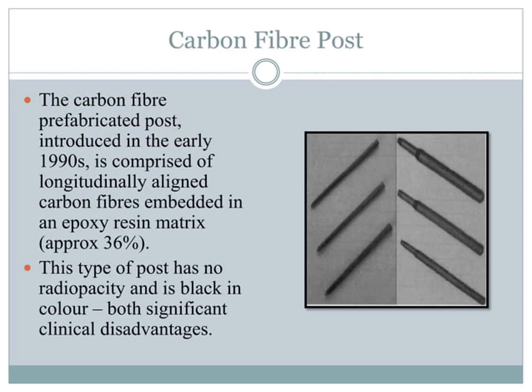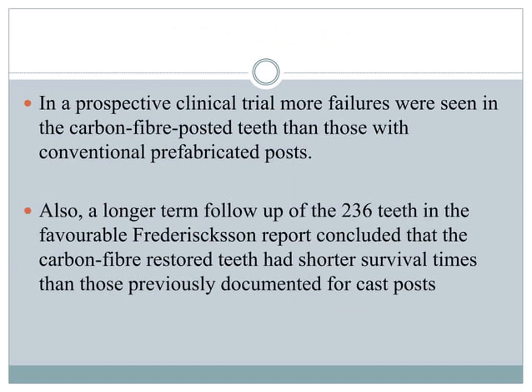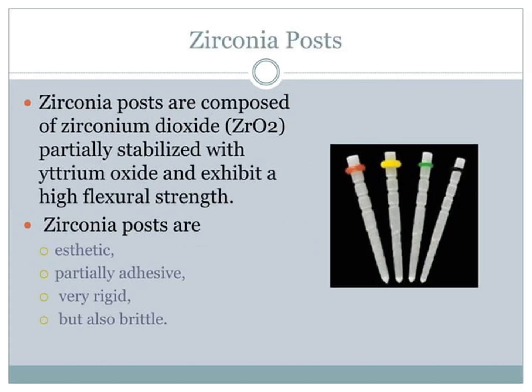Carbon fiber posts were introduced in the early 1990s and are comprised of longitudinally aligned carbon fibers embedded in the epoxy resin matrix. This type of post has no radiopacity and is black in color, both significant clinical disadvantages. In the prospective clinical trials, more failure was seen in the carbon fiber reinforced posts than those with conventional prefabricated posts. Also, a long-term follow-up of 236 teeth in the favorable Fredrickson report concluded that the carbon fiber restored teeth had shorter survival times than those previously documented for the cast posts.